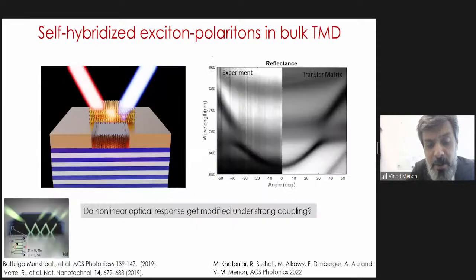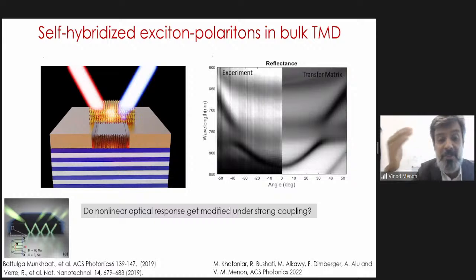So what we did was we took a bulk material. So this is your bulk material. So this is some 2D material. And it turns out that because these materials absorb light so much, and because they're around the exciton resonance, they have a very large refractive index. What happens is light gets trapped by itself. You don't need a cavity. You just take a bulk of this material. It's not a direct band gap. Nevertheless, you can trap light inside the system. They've got a very high refractive index.